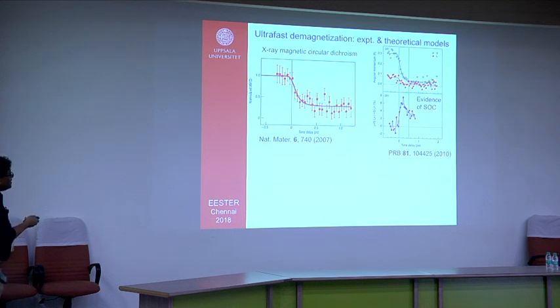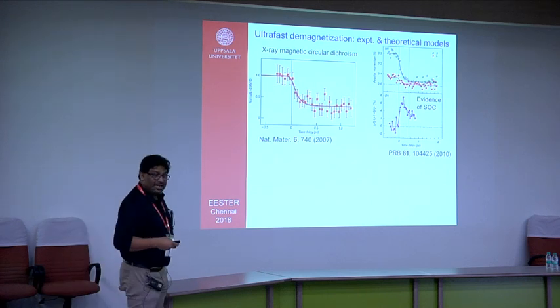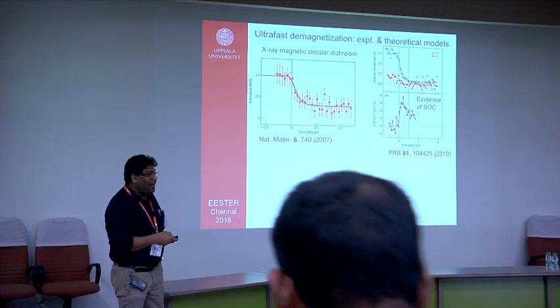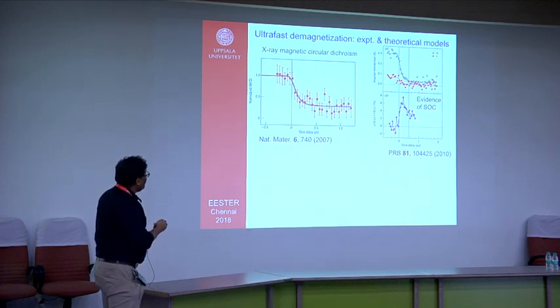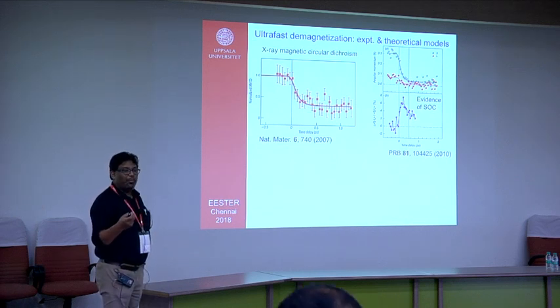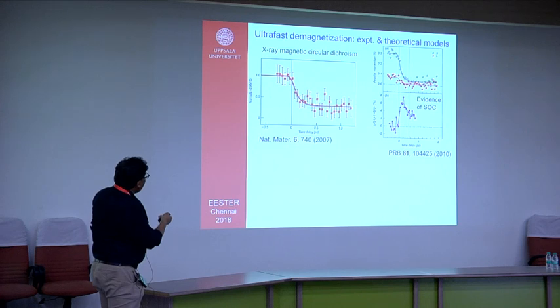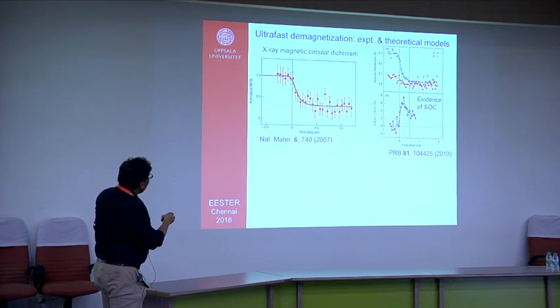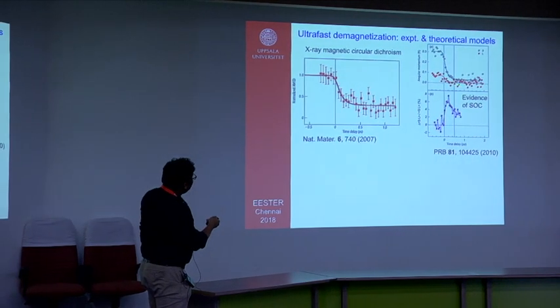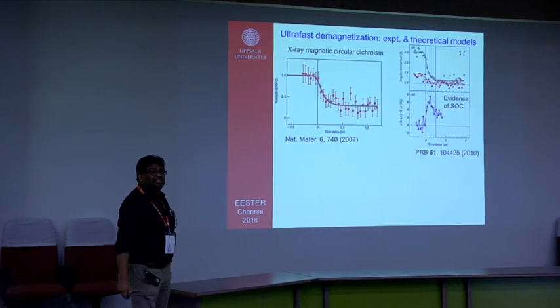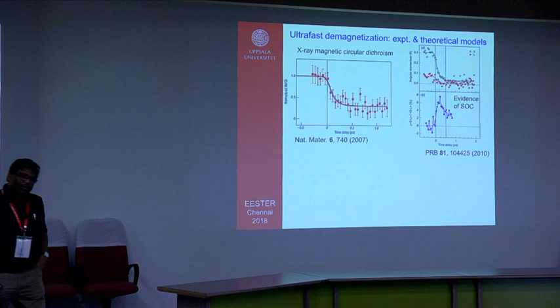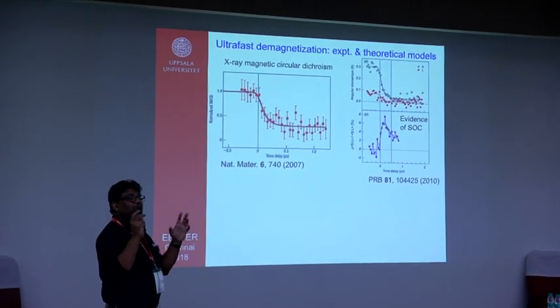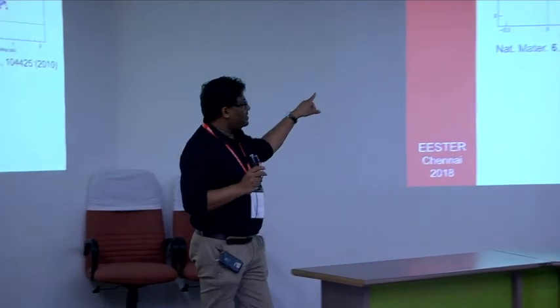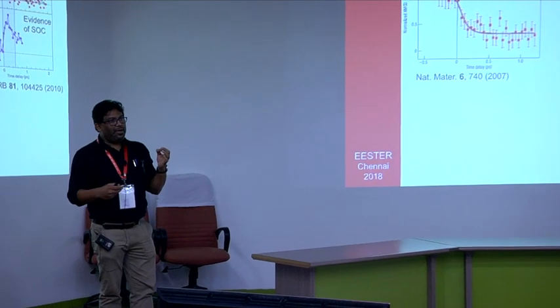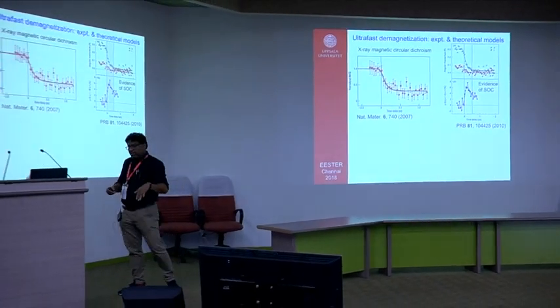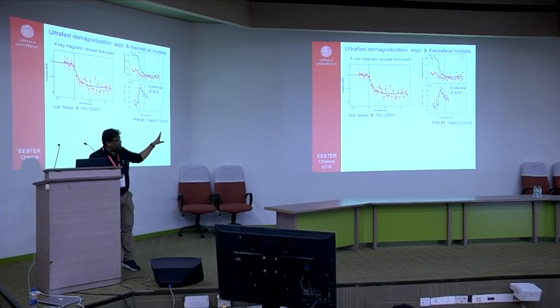Now this is even more advanced because this is measured as a function of time. Usually it is measured in a static way, but this is measured as a function of time. And some clever people can actually find out the components of the spin and orbital angular momentum like this. This is the spin angular momentum component, how it decays with time. This is the orbital angular momentum component, how it decays with time. And from there, you can estimate that there is a strong coupling between spin angular momentum and orbital angular momentum. Spin orbit coupling. So that means it tells us that in this highly non-equilibrium situation, spin orbit coupling is extremely important. So this is direct experimental evidence of that.